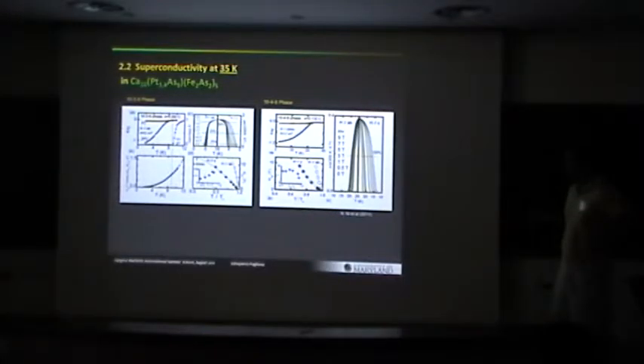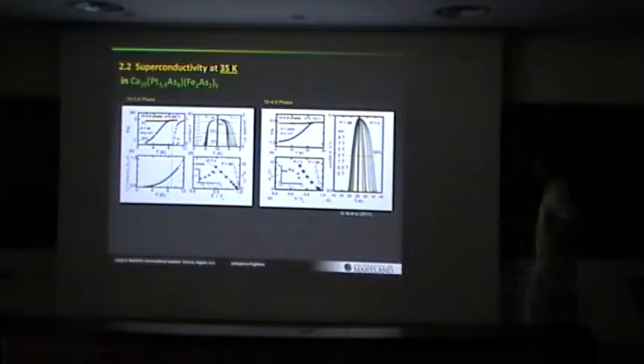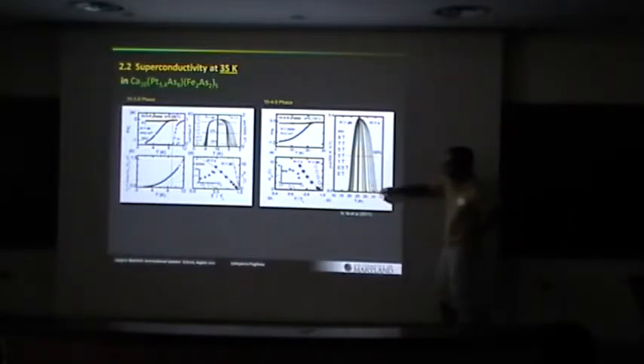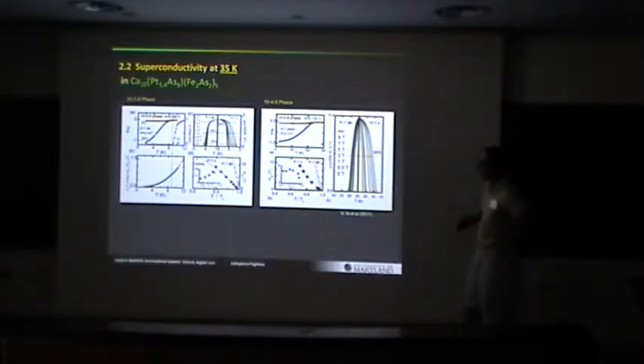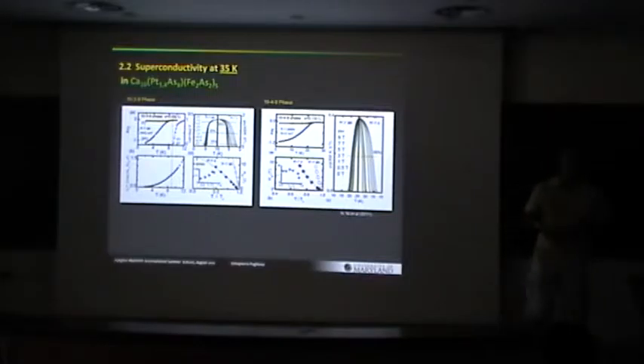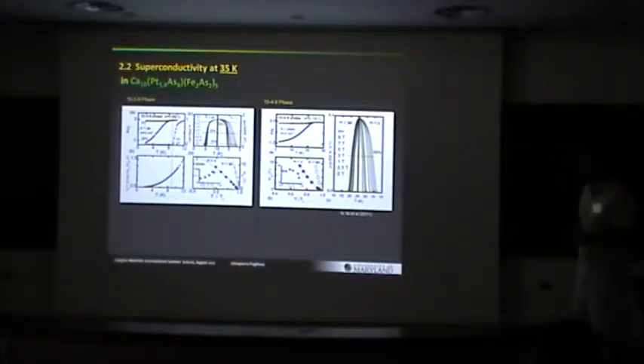Okay, a few more data sets. HC2 in, let's see. This is a roughly 10 Kelvin superconductor. HC2 here is 10 Tesla, maybe 30 Tesla or something like that. In this case, it's a little higher. TC is a little higher here. Okay, so similar properties to the iron arsenides, more or less.